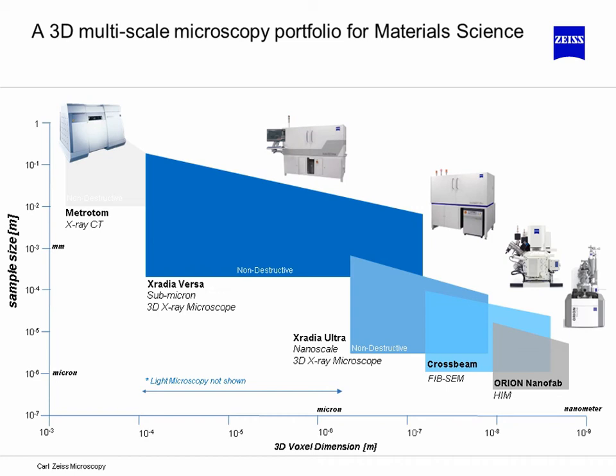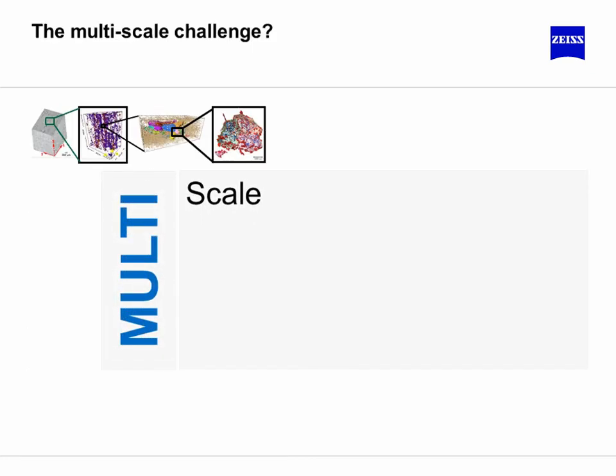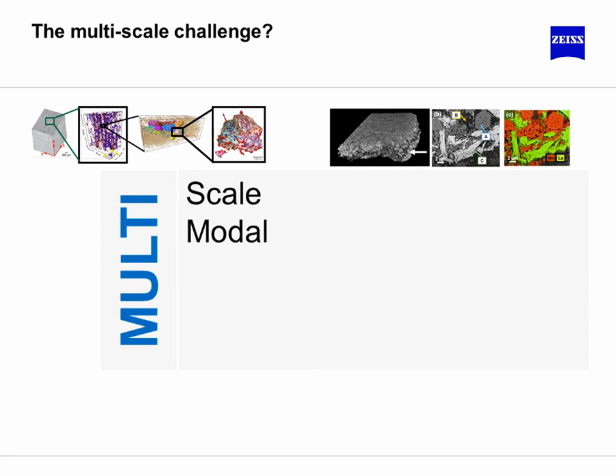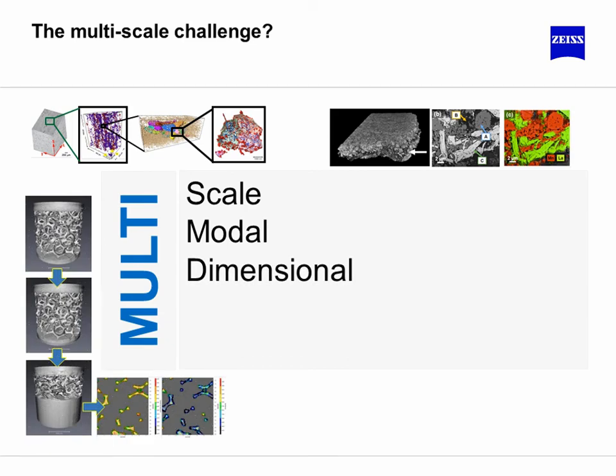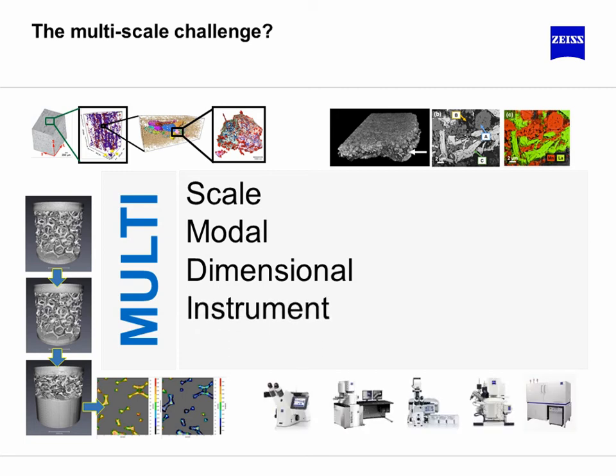You saw at the very beginning I showed a technique that utilized all three of these techniques, Versa, Ultra, and Crossbeam, to look at corrosion in magnesium alloys, which really exhibits multiple stages of characterization along this step. Now, this multi-scale challenge obviously spans different scales, but it does require multiple modalities as well. So as modalities, we mean different contrast mechanisms, whether it's absorption or EDS spectroscopy or polarized light microscopy. They're all helpful in one way or the other to fully characterizing the system. But multiple dimensions are often required, such as 2D is often sufficient, 3D is often desired, and even 4D gives you a real insight into the behavior of materials over time.